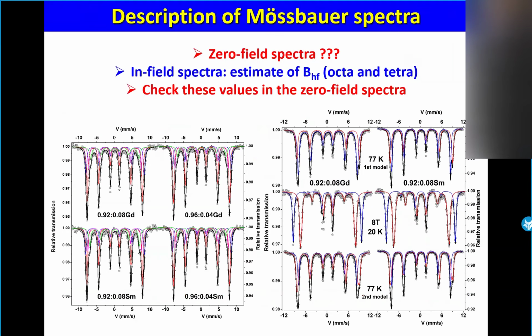So, as I mentioned before, we have some ferrites. The composition is with gadolinium or samarium. And it is clear that we perform at room temperature nanoparticles, so plenty of components without physical meaning. Okay, to describe, but it was not possible to distinguish carefully and accurately tetra and octa. In the spectrum at 77 K, we can see some shoulder. Wow! It's possible to put 2 components and to have directly the proportion of tetra and octa. But maybe it would be better to perform in-field Mössbauer spectra, according to what I mentioned before the break.